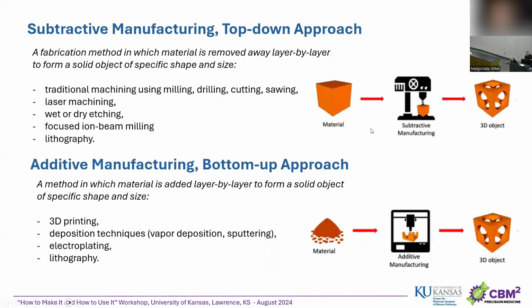In this original picture, if you look at those cartoons online, it shows that in traditional manufacturing you start with material, you cut it out, and you produce a lot of waste, because everything that you cut out becomes waste. When you do 3D printing, you only assemble it, so there's barely any waste. There are some issues with that I didn't discuss. The advantage of 3D printing at mass scale, when you have this big bed of particle polymer that you're sintering to create your 3D object, is that you can reuse everything that wasn't sintered and feed it back in, and you keep reusing this. So you're saving a lot of material cost.